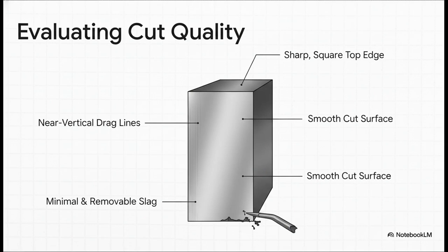You know, the great thing is, the finished cut gives you direct feedback on your technique. A proper inspection looks for four main things. You want drag lines that are uniform and nearly vertical. The cut surface itself should be smooth and flat. That top edge needs to be sharp and square with no rounding. And finally, any slag on the bottom should be minimal and super easy to just chip away. If you see any problems with these, it's a dead giveaway that something was off: your travel speed, your torch height, or your gas pressures.